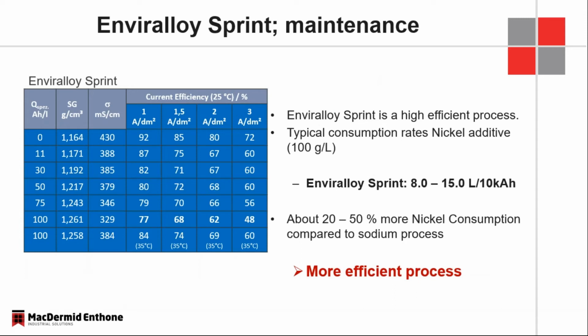So this also goes to efficiency. This also talks about specific gravity. And since it is the #1 cost driver, when we talk about 8 to 15 liters per 10,000 amp hours, we're talking about 20 to 50% more nickel consumption compared to sodium process. That's because it's more efficient. We don't need to have sticker shock by looking at that, but it's something that needs to be noticed.